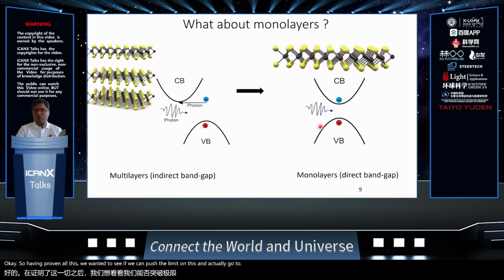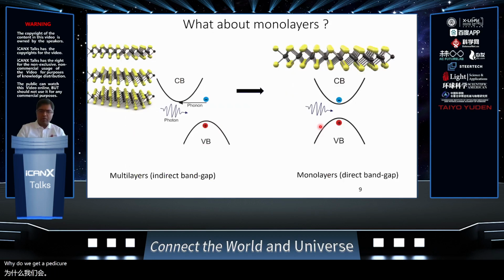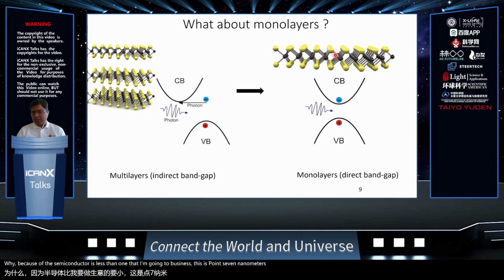So having proven all this, we wanted to see if we can push the limit on this and actually go to monolayers. Why do we care about monolayers? We do care about monolayers because when we go to monolayers, you do get a direct to indirect to direct band gap transition, and you actually get much larger emission efficiency coming out of your material now. So that is great. The problem is trapping light in monolayers is even harder. Why? Because the semiconductor is less than 1 nanometer in thickness. This is 0.7 nanometers, extremely hard to trap light.